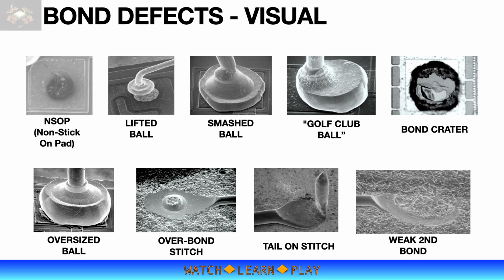This is one of the most common bonding problems. On this defect, there is an impression of the free air ball impact onto the bond pad, but the first bond did not stick. Usually the mash ball will be present on the lead. If there's no impression on the bond pad, it could likely be that the bond pad is passivated or the bond was off target.